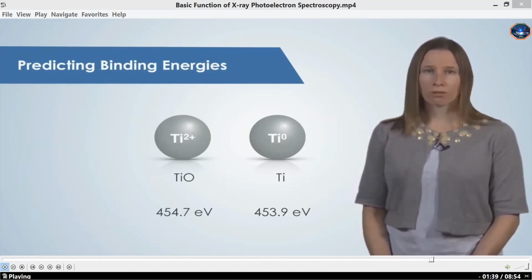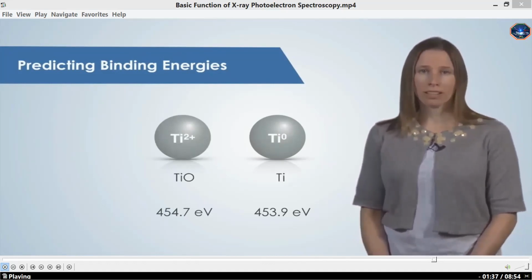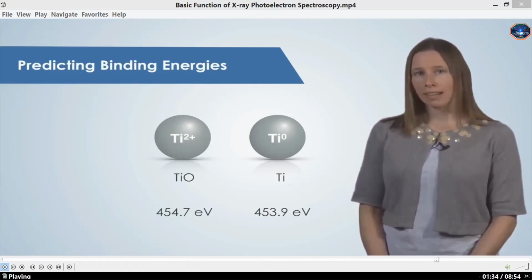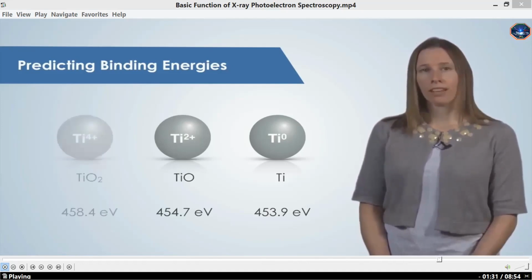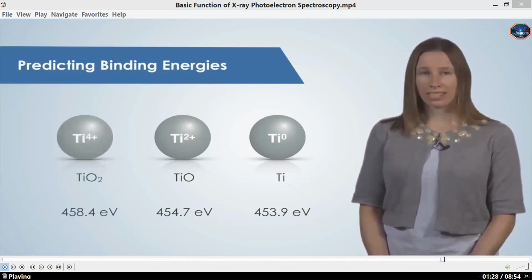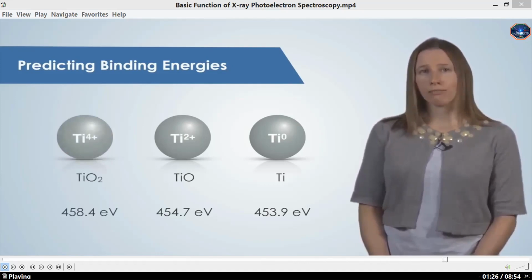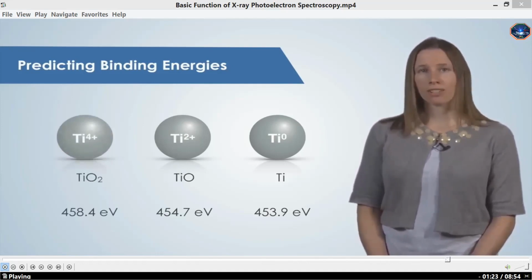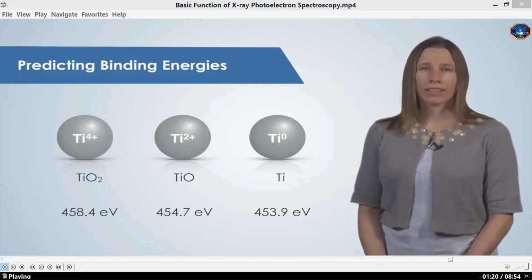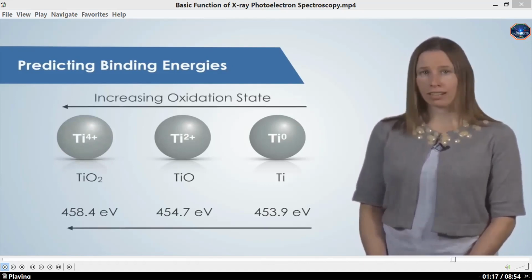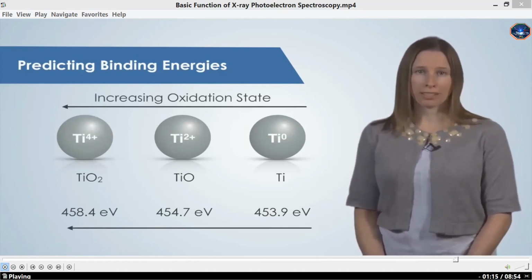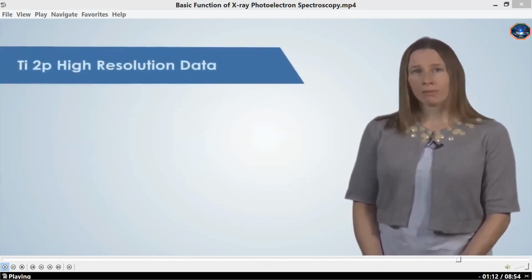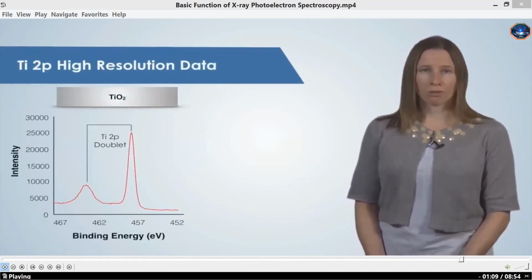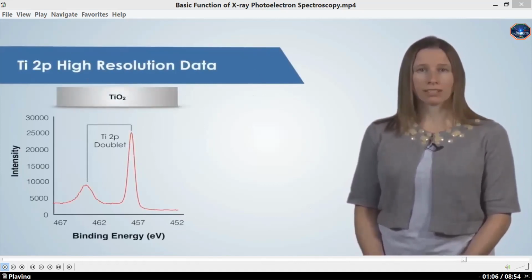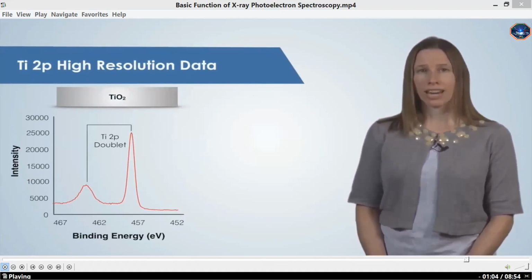In the 2+ oxidation state, 2 electrons have already been removed from the titanium. It is therefore more difficult to remove an electron from titanium 2+ than from elemental titanium, and the binding energy is a bit higher. Finally, titanium dioxide, or TiO2, contains titanium in the 4+ oxidation state, and the binding energy shifts to an even higher value. In general, as the oxidation state for an element increases, so will the binding energy. The titanium 2p data for TiO2 is shown here, and we observe the expected doublet with peak positions consistent with titanium in the 4+ oxidation state.